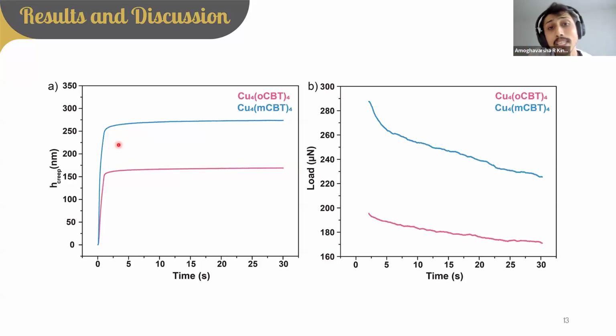If we are observing the changes in displacement, it is called a creep measurement. Here we can see that after the initial indentation, there is no change in displacement for up to 30 seconds, indicating that my material is strong and is stable under constant stress.